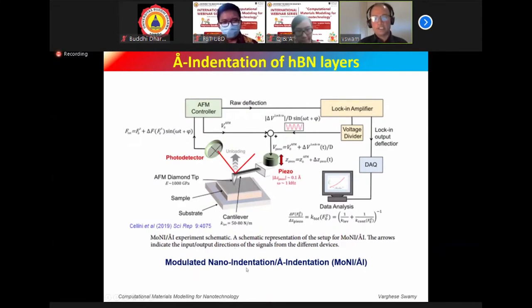It's called the modulated nano indentation, Ångström indentation. Essentially, it uses a combination of AFM, atomic force microscopy tip, which is Ångström scale, very small scale, and that can penetrate very small thickness, because these materials are atomic thickness materials. So we are talking about 0.3 Ångström or something, and then it can probe the material.